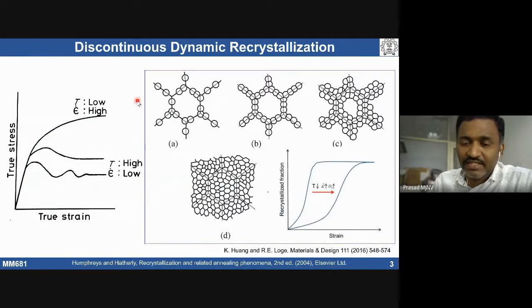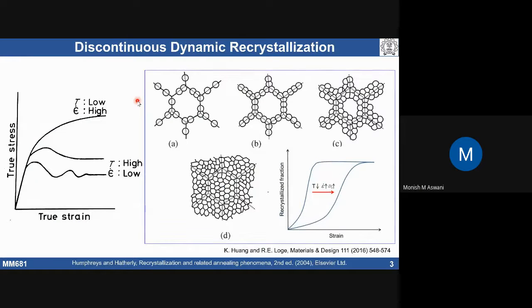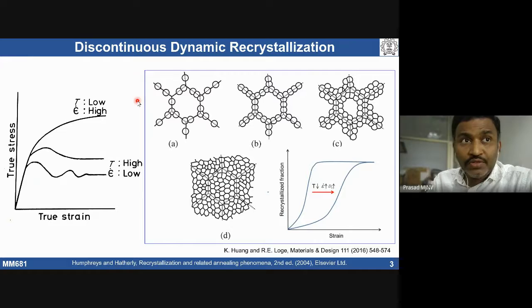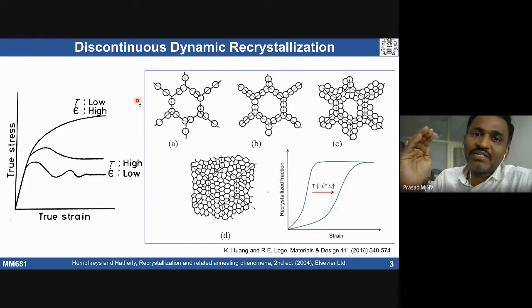Sir, DRV happens at a lower temperature than DRX, right? It's not necessarily so. It depends on the stacking fault energy of the material. In high stacking fault energy materials, dynamic recovery is going to happen first. What we are talking about here is static recovery and static recrystallization. Typically, we see static recovery first at low temperature, followed by static recrystallization at a little higher temperature. When you say dynamic recovery and dynamic recrystallization, dynamic recovery usually happens when there is a high stacking fault energy, where recovery happens first. That means we don't have enough energy driving force for recrystallization to happen.